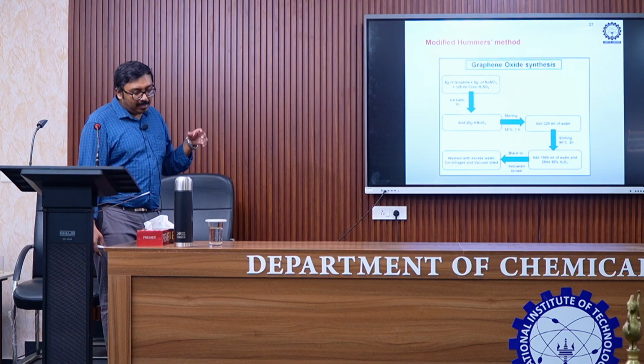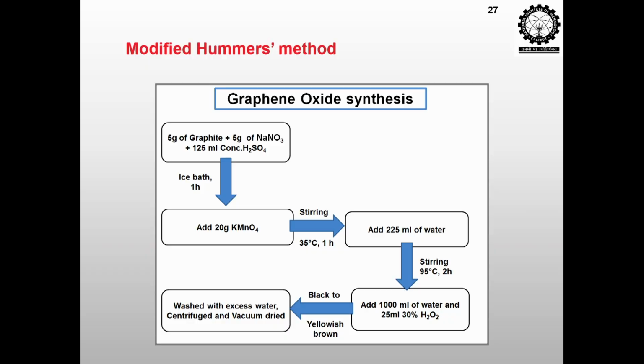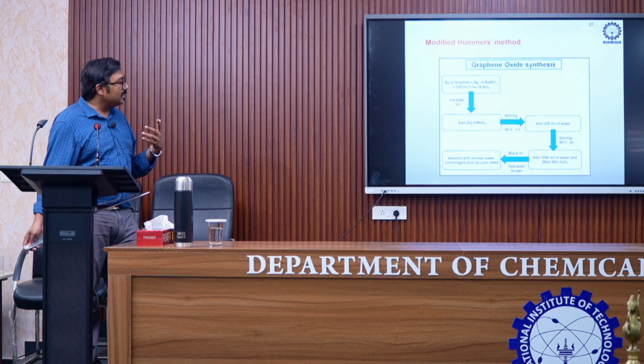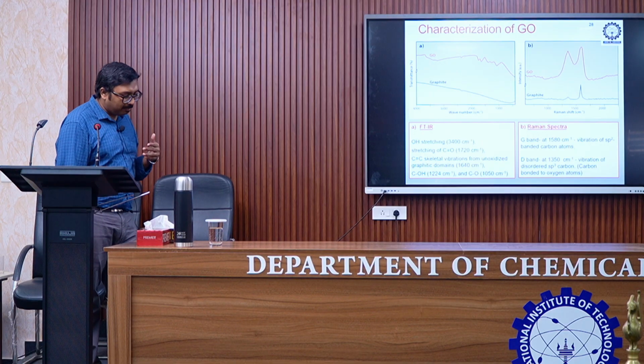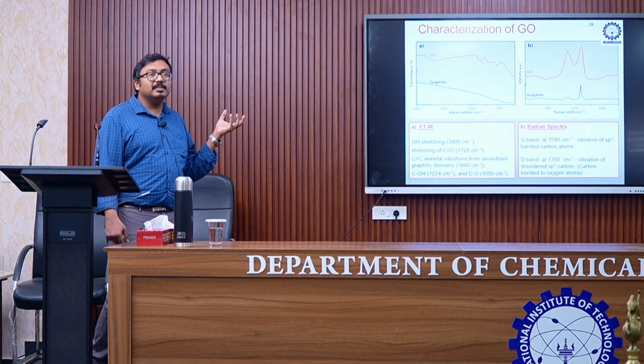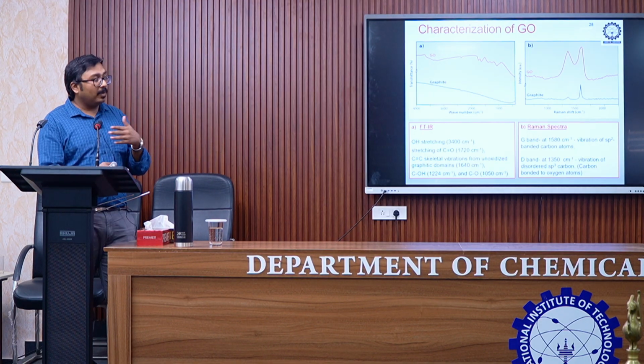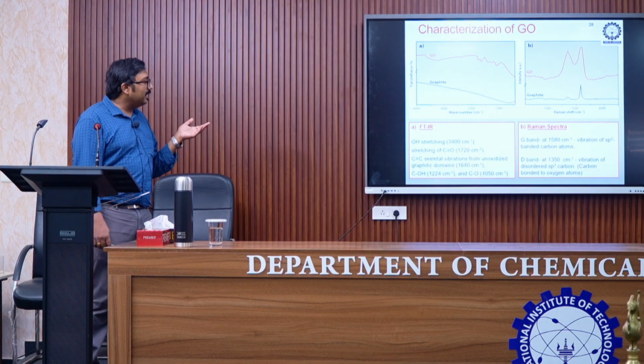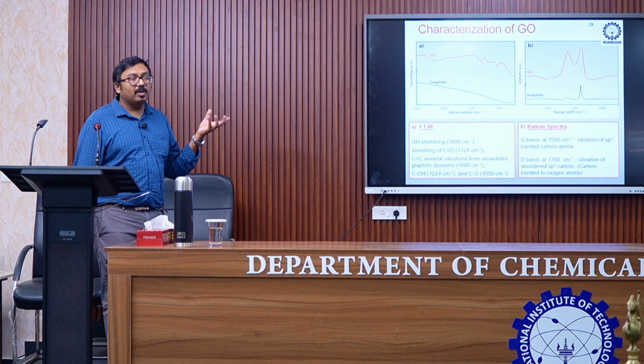So we have prepared graphene oxide. Graphene oxide today is well known and is widely used in a large number of applications. We used the conventional chemical synthesis route. And once that was done, the graphene oxide was characterized. I am not going into detail on the characterizations because that is not the point here now. They were extensively characterized and identified that the graphene oxide is formed.